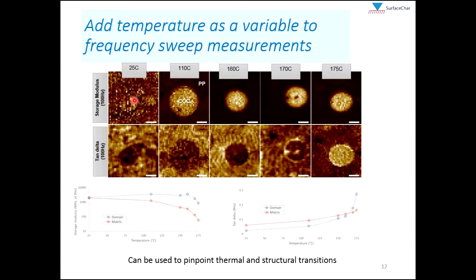So what we see in the storage modulus maps is that the cyclic olefin copolymer at high temperature is much stiffer than the polypropylene. And so these actually diverge. Their storage moduli diverge as we increase the temperature. The loss tangent has a very different story. So the cyclic olefin copolymer has a lower loss tangent than the polypropylene at room temperature. But as these get heated and we approach the glass transition temperatures of these two materials and even pass through them, we can see that they become very close to each other. The loss tangent becomes very close, and then they actually invert. So now the loss tangent here for the COC is higher than that of the polypropylene matrix.